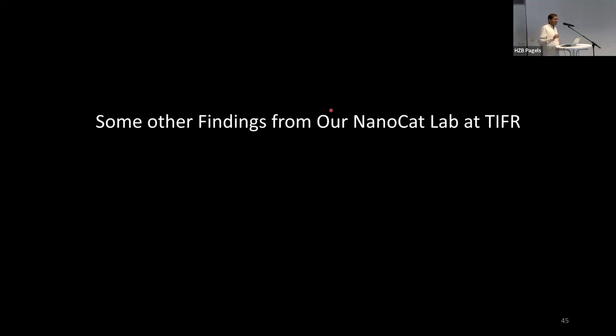So one of the statements I made in my talk is that silica doesn't do anything, right? It's a passive material. You need to put active sites. And most of the time, active sites, you know, are metal nanoparticles. And we all know metal nanoparticles are very reactive, but they are also very unstable. They oxidize, they sinter, and activity of the catalyst goes down. So then we ask this question, how do I make the DFNS, the silica, active without putting metal nanoparticles? If there are no metal nanoparticles, there's no issue of oxidation or sintering.